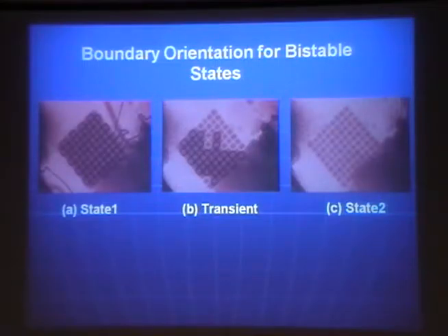fairly big. We can see individual domains, but by shrinking the domain size, the boundary contrast tends to dominate the whole contrast. This becomes darker and darker, this becomes brighter and brighter, giving rise to the final bright and dark images. And what is really important is these dark lines here are connected with a bulk disclination, surface disclination line. The disclination line is running this way and going somewhere and probably coming back right here.